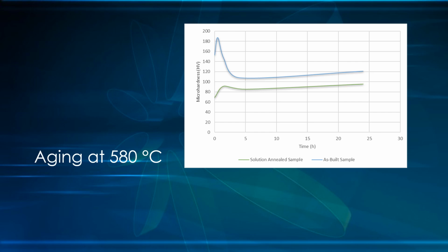So we can see that the blue line relative to the as-built sample shows that the peak of the microhardness, the maximum hardness, is reached very quickly. And then we have a sudden decrease of the hardness due to the overaging phenomena. While after solution annealing, we have again the formation of a hardness peak, but the hardness of the alloy is always much lower than the one that has not been subjected to the solution annealing.